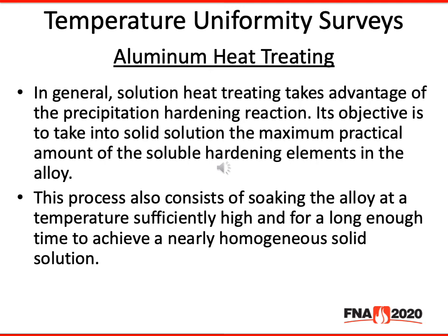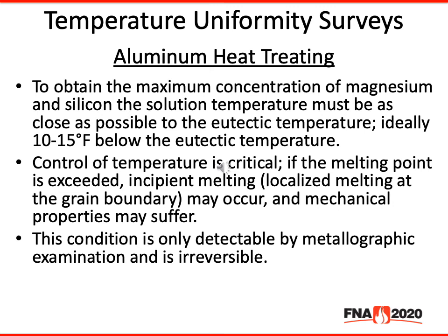In general, solution heat treating takes advantage of the precipitation hardening reaction. Its objective is to take into solid solution the maximum practical amount of the soluble hardening elements in the alloy. This process also consists of soaking the alloy at a temperature sufficiently high and for a long enough time to achieve a nearly homogeneous solid solution. To obtain the maximum concentration of magnesium and silicon, the solution temperature must be as close as possible to the eutectic temperature, ideally about 10 to 15 degrees below the eutectic temperature.